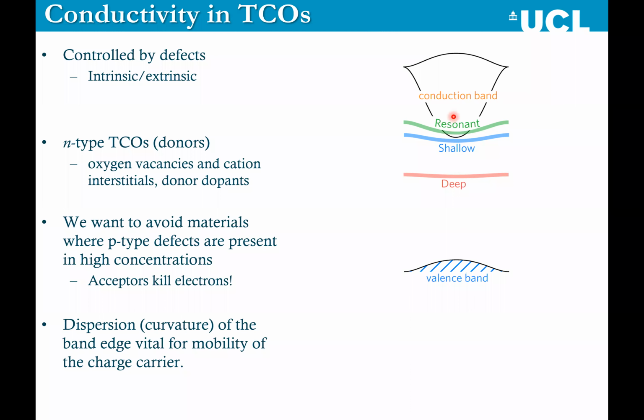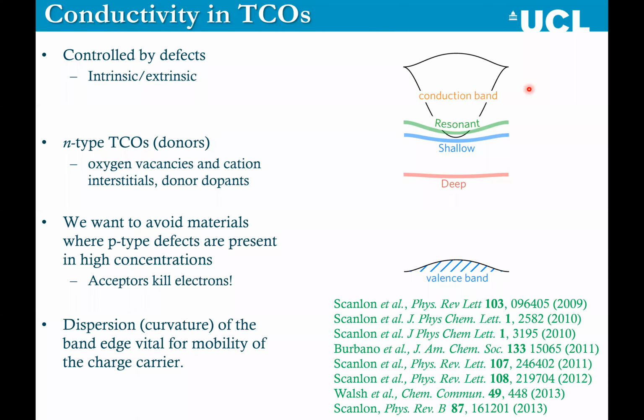But we also need very good dispersion or curvature of the band edge. So the curvier your conduction band minimum is, the lower the effective mass, the higher the mobility of the charge carrier. We know from simple physics that conductivity equals mobility times carrier concentration. So the more extra electrons you can get in there and the higher the mobility, the higher the conductivity you will have. So we spent about 10 years doing this.